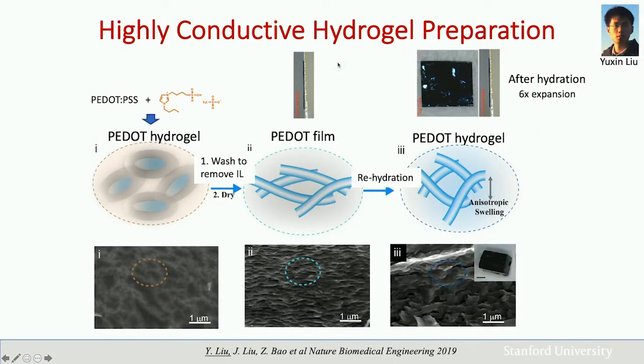So the conducting hydrogel that we finally prepare for interface with biological system, actually, first we form this hydrogel with the ionic liquid, and then we evaporate the water and wash away the ionic liquid. So this will condense into a dry film. And then we can subject this very dense film under conventional photolithography and patterning. So we can pattern this conducting material down to micron feature size. And then we expose this patterned structure with water. And then once it's exposed to water, it will have an expansion. So you see the side view of the expansion. The volume will expand by 6 times. So great expansion of the volume and a lot of uptake of water into this conducting hydrogel.